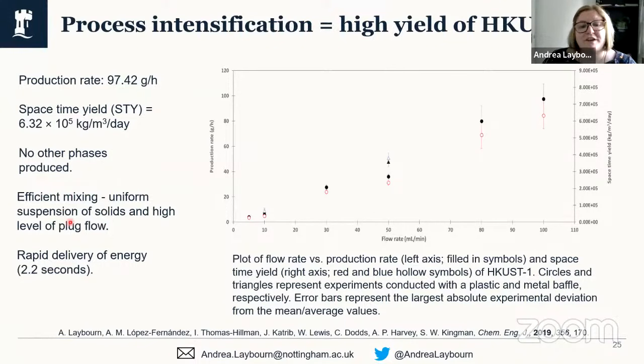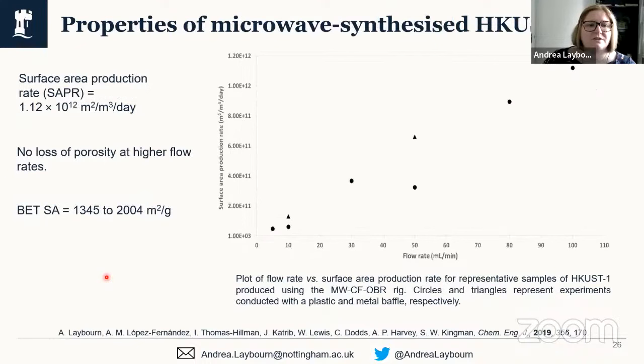And we were also able to visually observe the efficient mixing and the uniform suspension of the solids. And I'll show you an example in a couple of slides' time as to the importance of that mixing. But to give you an idea of how fast these reactions were, at the highest flow rate, so up at 100 mL per minute, our energy delivery was at 2.2 seconds, which is the fastest reported synthesis of MOFs that I'm aware of to date. So extremely fast reaction time. So it was great to see that we were able to produce the material at these astonishingly fast timescales.